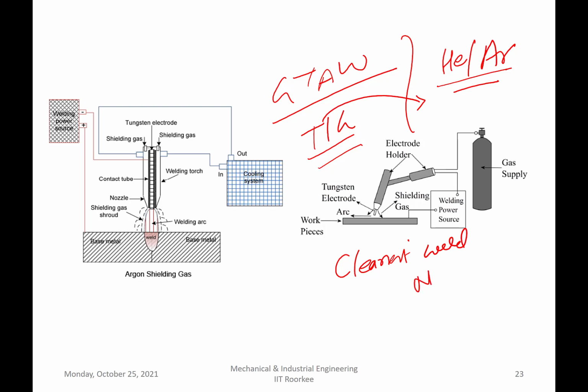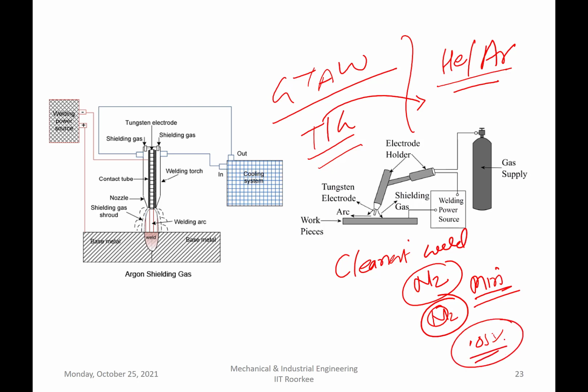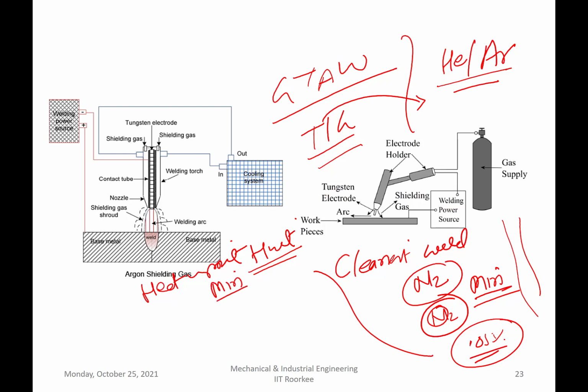Means the oxygen content and nitrogen content in the weld metal are minimum among all arc welding processes. It is around 0.05% of, say, oxygen or nitrogen. So in terms of cleanliness, the GTAW process offers a very clean weld. This is one. And the heat input supplied is also minimum in this case, because it uses very low current.